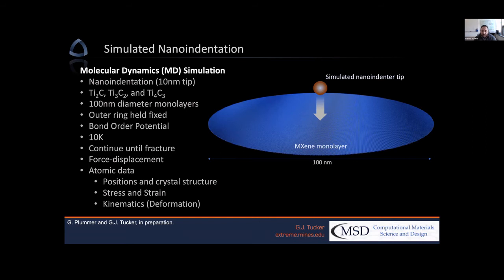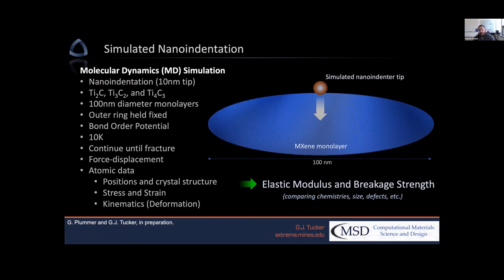And then we did this at 10K. The simulation was performed at 10K, and we continue this until fracture occurs. And then out of the simulation, we get force displacement data, and we have all of the information for every single atom. This includes positions of the atoms, the structure of the atoms, the stress and strain of the atoms, in addition to some kinematic information that we can calculate in a post-processing way. And what we're hoping to do here is to find out the trends in elastic modulus and the breaking strength of these MXenes, looking at various variables along the way.